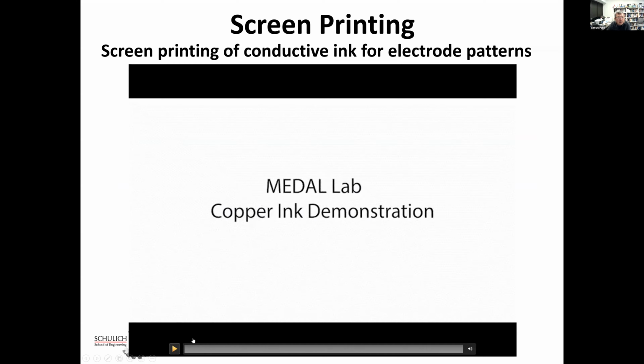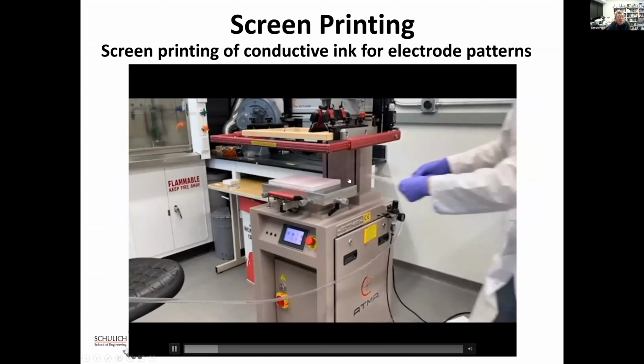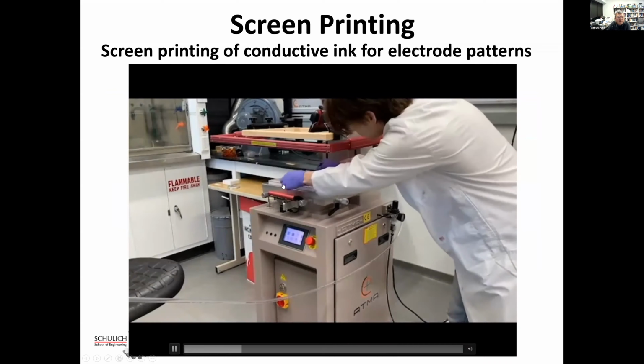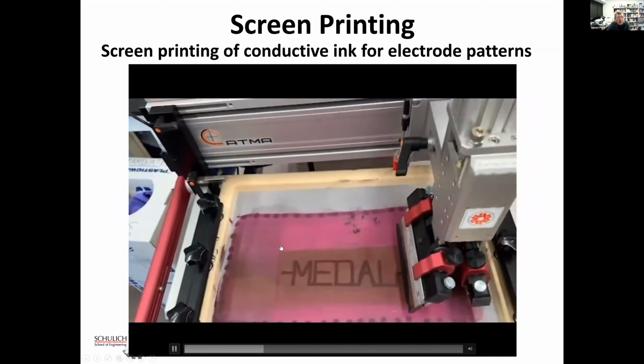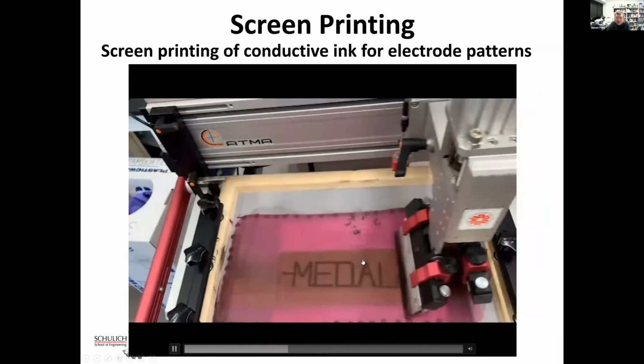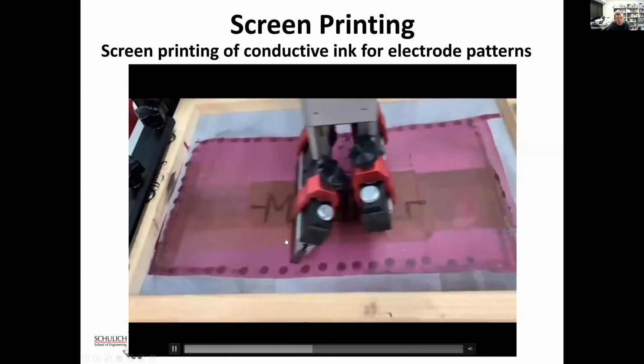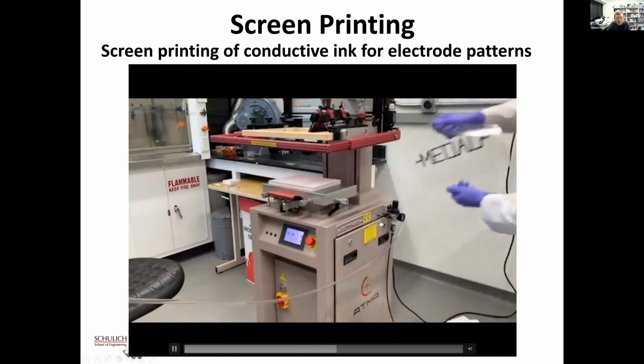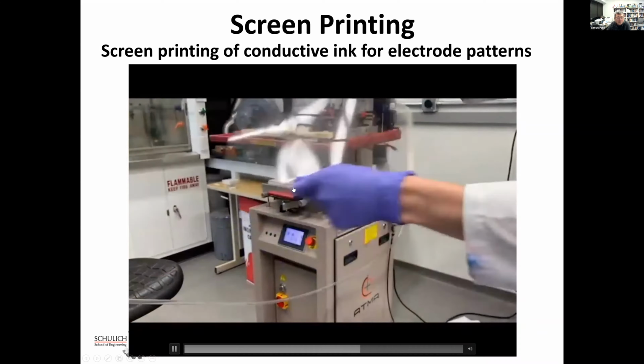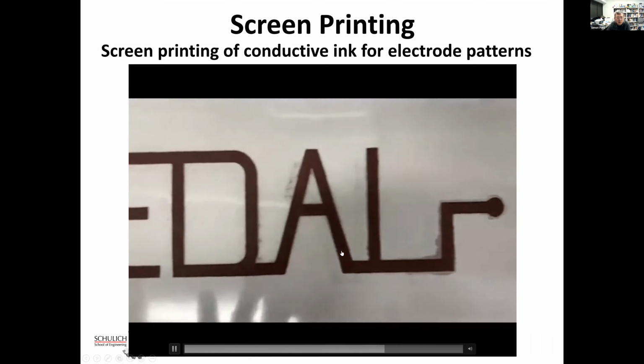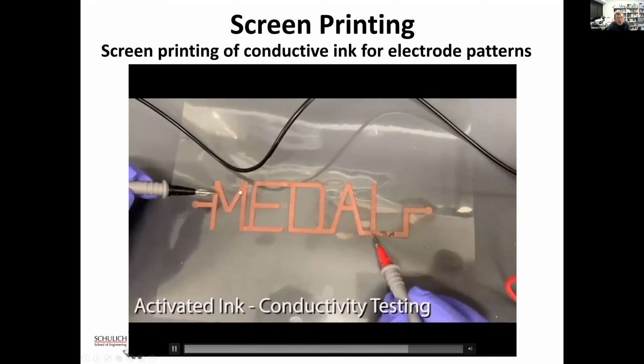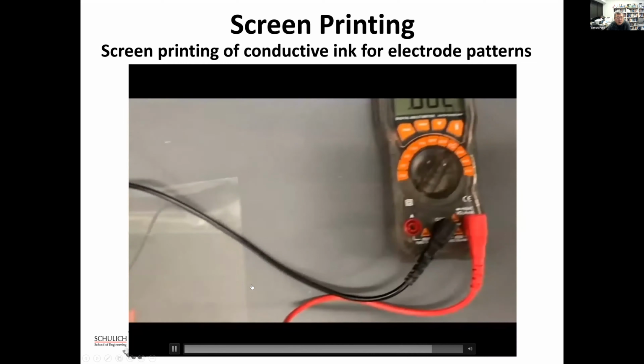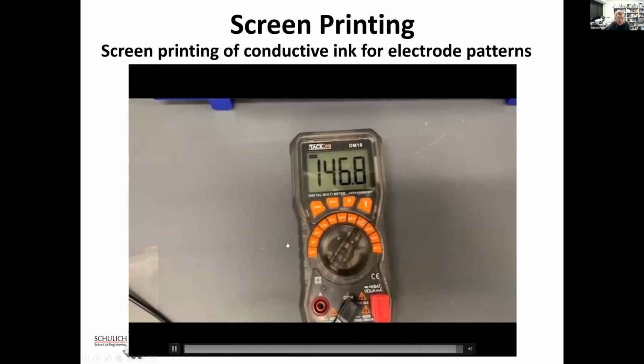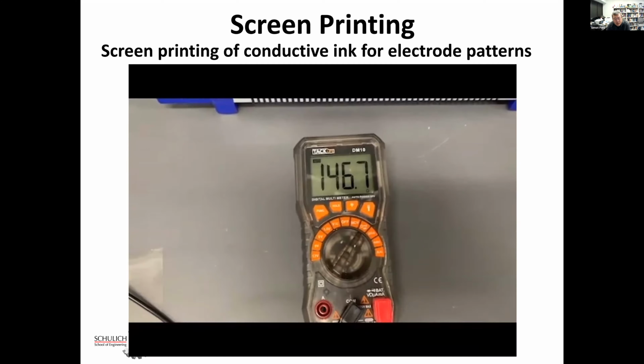And this is a demonstration of screen printing. Here, we are using a screen printer. We are putting in a very thin, flexible plastic sheet. And this is nothing more than a t-shirt making screen printing machine. And instead, we put our own ink. And when we take it out, it's kind of a dark brownish color. It's not conductive. What we do is we bring this to flash, and we go through sintering. And if we sinter, now we have a nice, shiny copper color. And you can see that it's fairly conductive. So we use these for mass production of different circuits and sensors and whatnot.